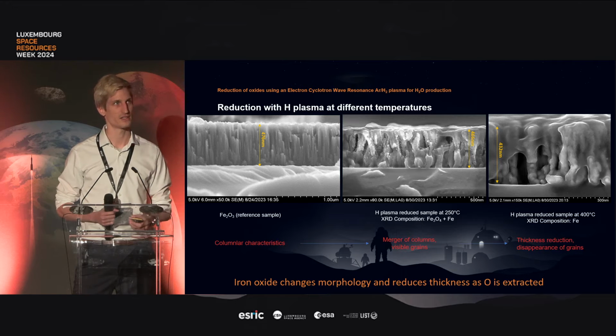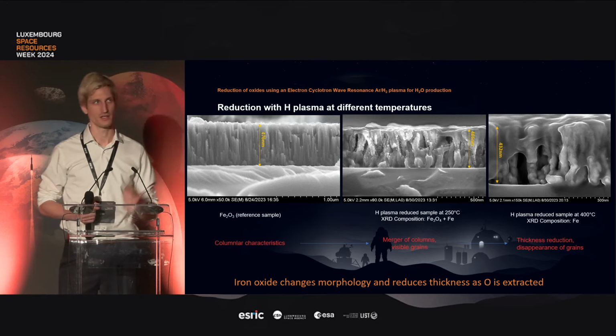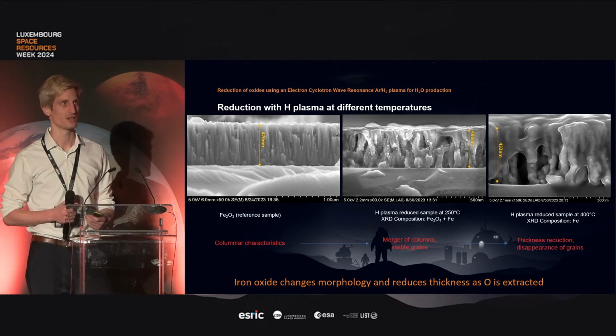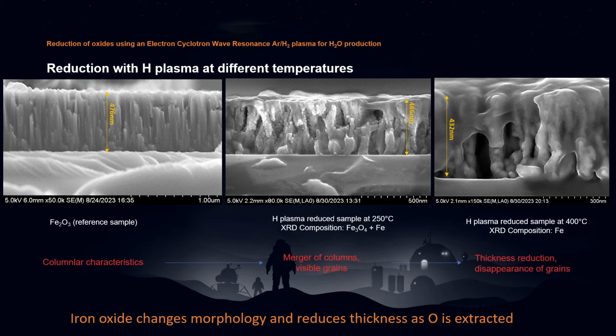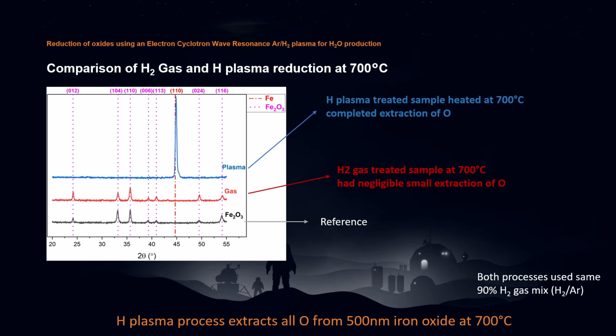And as we can see on the right, as soon as we treat the sample, in this case, we also used heating of the material, and we reduced it with hydrogen plasma for 2 hours. We can see very strong indication of morphological change. We see formation of porosity. We see the formation of these columns as well, and also grains appearing.